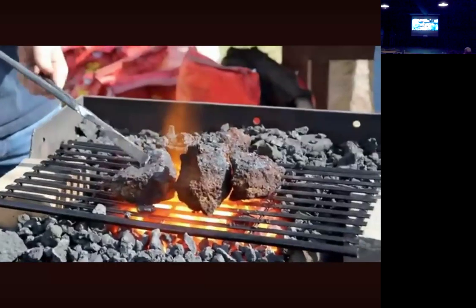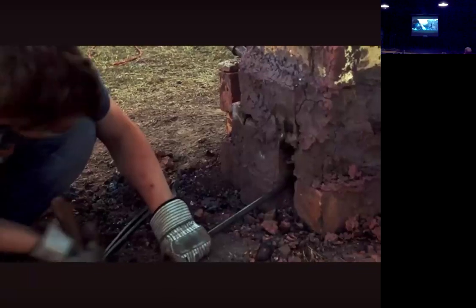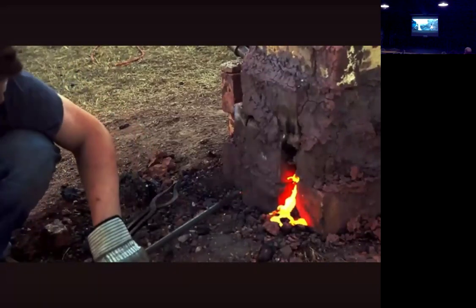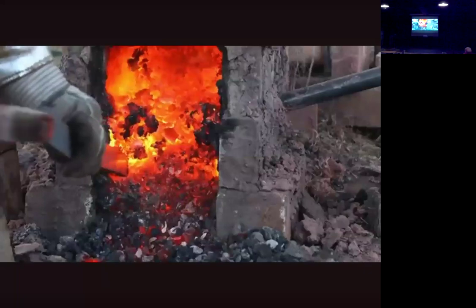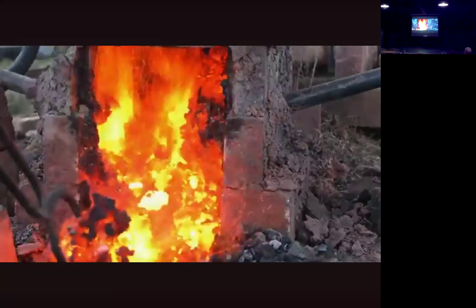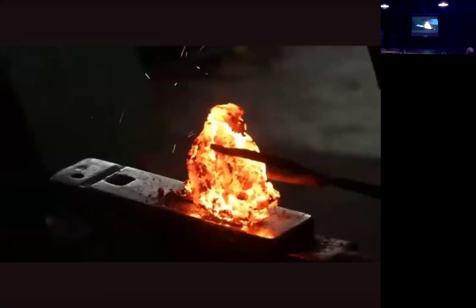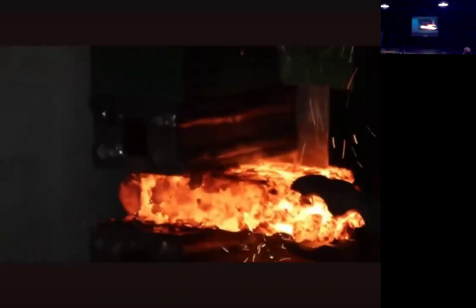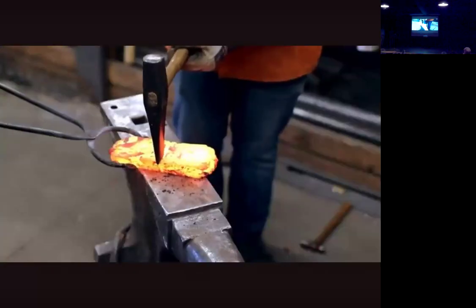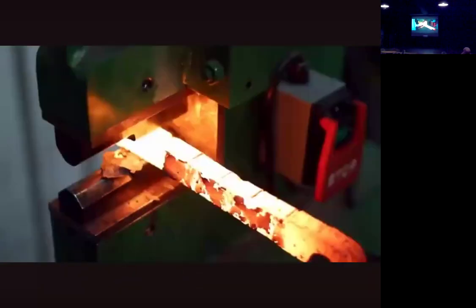Once the ore was collected, it was roasted, crushed, and fed into the bloomery with charcoal to begin smelting. The reaction was controlled by adjusting airflow through the tuyères, and slag was periodically tapped to prevent them from clogging. Once the reduction reaction was complete, the bloomery was dismantled to remove the bloom. The bloom was repeatedly folded to create a billet with fewer impurities. Unfortunately, the forging characteristics remained poor, and X-ray fluorescence, metallography, and energy dispersive spectroscopy revealed the presence of high residual sulfur and impurities that made the billet unsuitable as a primary blade material.